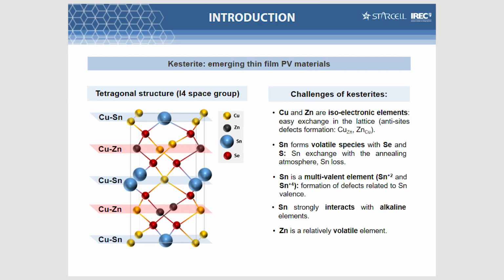And tin is a very problematic element because it has different characteristics that make it a complex element to work with. In particular, tin forms volatile species with selenium and sulfur, so it is really very complicated to control in our material. It is a multivalent element, so we always have the risk of forming reduced tin species that can be really problematic because they introduce deep defects, and tin strongly interacts with other elements like alkaline elements that are very relevant for chalcogenides. So the control of tin really is one of the big issues also in this technology. And in terms of zinc, it is probably the least problematic one, but it can also be volatile, like metallic zinc. So all the technologies that use metallic zinc during the preparation of Kesterite have to consider this as well.